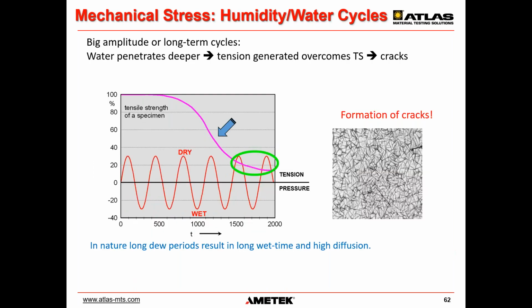No cracks, as expected. But now the amplitude is increased. The acrylic melamine systems crack after 2000 hours. Water penetrates deeper, the tension is higher than tensile strength. Formation of cracks is observed. The consequence for the paint manufacturers back then was the development of clear coat systems with lower TGs and higher tensile strengths. Why? Higher tensile strengths to stay out of the critical conditions, and lower TG at about 20 Celsius